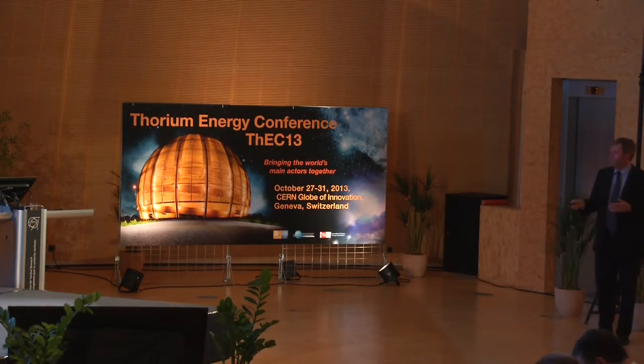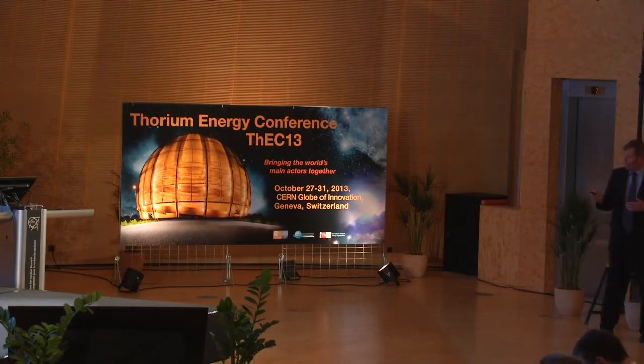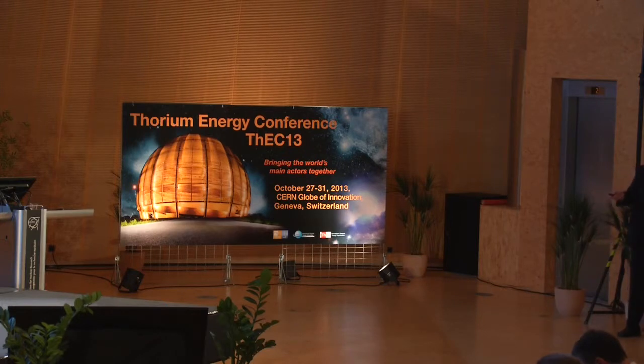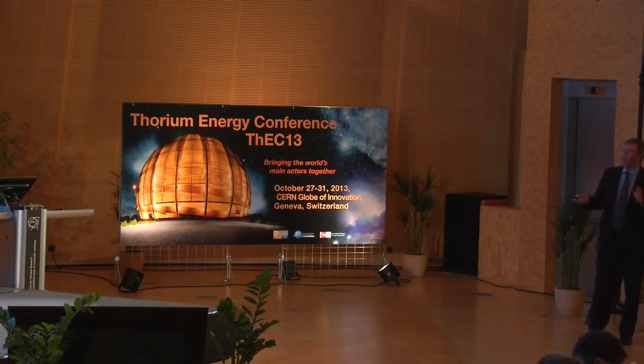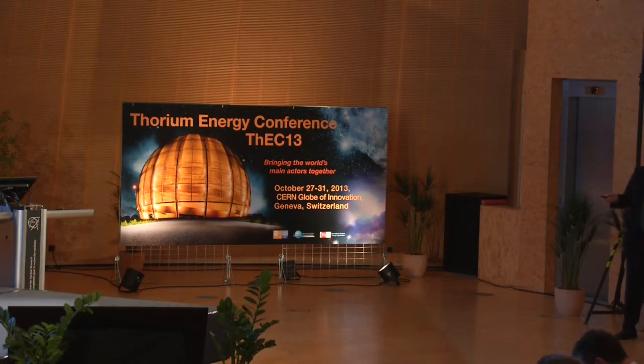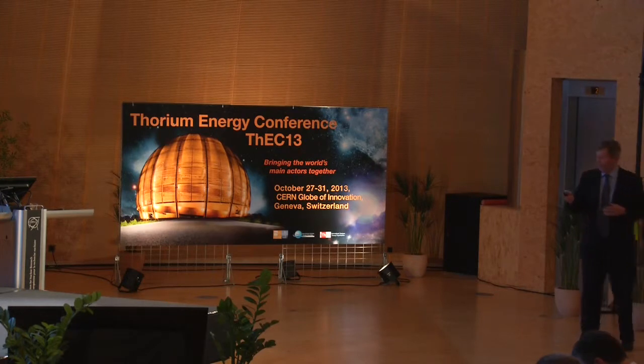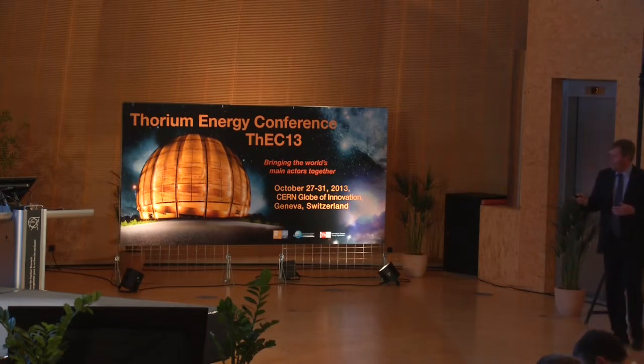So these are the types of properties that you're interested in. So we know, for example, for this lithium fluoride, thorium fluoride, that the phase diagram looks like this. So this is the liquid region up here. This is this eutectic composition. And you remember that I was talking about operating this reactor in this sort of temperature range between about 650 and 750 degrees Celsius. But you can see the sorts of issues which might well arise, because if the composition of the melt was to change by not too much, you start to run into freezing. And clearly that would be very undesirable if something like that started to happen, in particular in your heat exchangers.